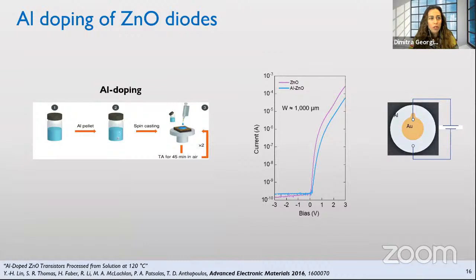Then, as a next step, we did some material engineering. We doped our zinc oxide with aluminum, again using a solution-based technique. We have an aluminum pellet dipped in the zinc oxide solution for some time, and then we spin coat this solution on top of the pre-patterned electrodes. We see that the rectification is again quite high, and we don't see much change in the DC characteristics of the diodes. The important thing comes when we shift to the high frequency characteristics of these diodes.